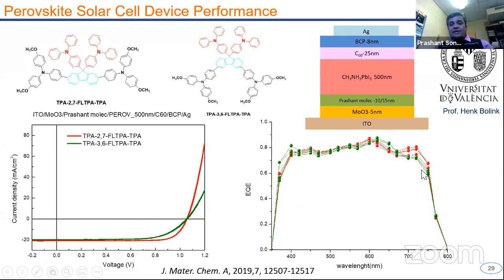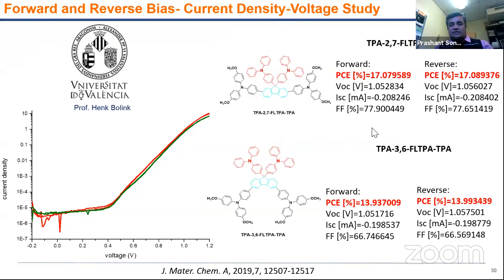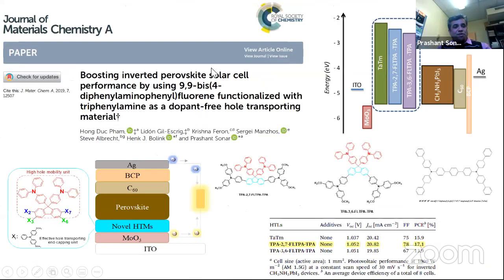And upon looking at the device efficiency data, this time also we can achieve 17% efficiency for the 2,7 compound, whereas in case of 3,6 we got 13 point, almost 14%. See, just by changing this position, there is a difference of almost 4%, and that clearly indicates how important molecular geometry or engineering is. This was published again in JMCA, and I'm just showing you a snapshot of this work, where we again got an open circuit voltage of 1.05 and PCE of 17.1 with a very high fill factor.